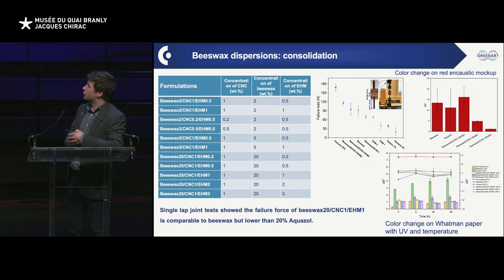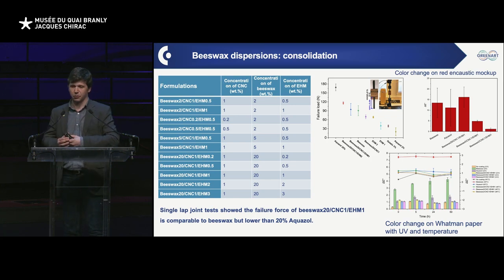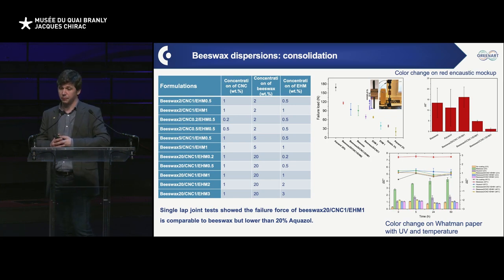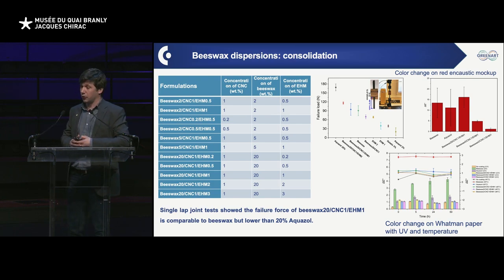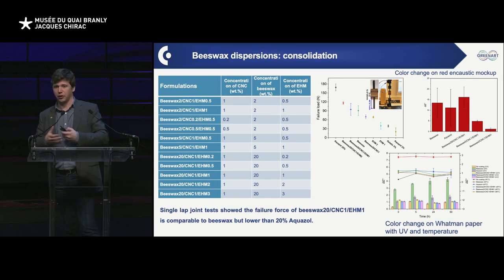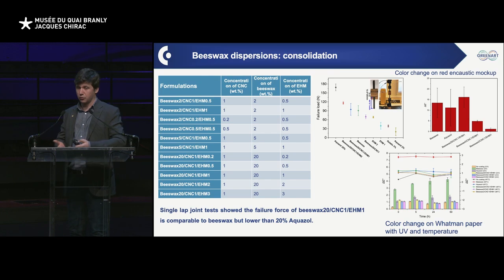Here we have just some other type of consolidants that we could consider. If you take Aquazol much more diluted, so 10 times lower in terms of dilution as compared to this one, well, we get a much meager result in terms of performances. So from that we were happy, and we thought, okay, we have this emulsion that may affect the color and the properties of the substrate. So we did some colorimetric measurements.